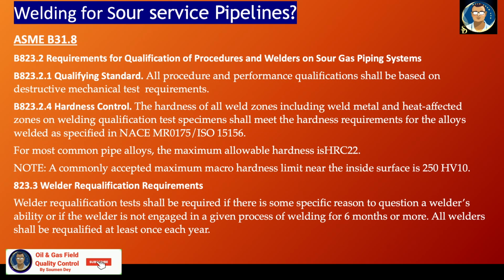Now, welding for sour service pipeline. This is an interesting subject because this is a job of construction contractors. As per ASME B31.8, as I mentioned just a few minutes before, you see the requirement of the qualification procedure. Always the performance qualification shall be based on destructive mechanical test requirement. Welder test also, the final acceptance is mechanical test.